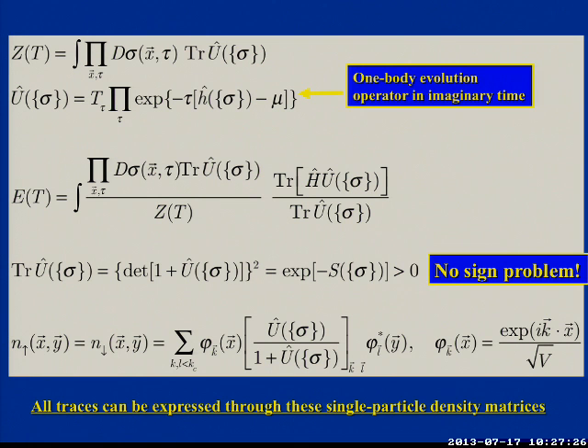Okay. So if we want to calculate the partition function, we can represent it like this, where this is the evolution operator. The evolution operator has a usual structure, time ordered, but the property which is nice here, that if you take the trace of this, it's positive. And this is due to the fact that we have equal number of spin up, spin downs, and basically the propagator for those, both of them are the same, and you have one determinant for one and one determinant for the other, you multiply them, you obtain a positive number. You don't have any complex numbers at this point.